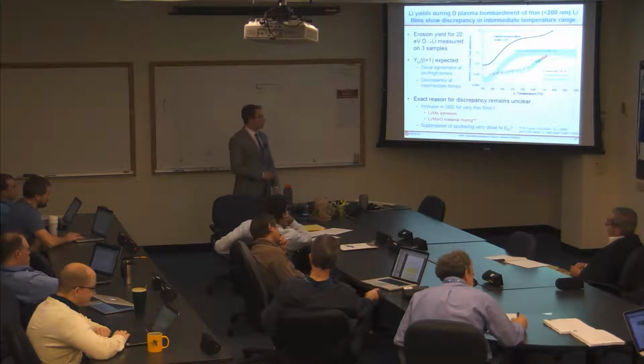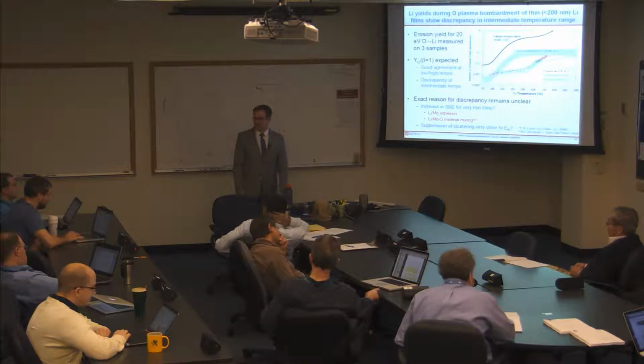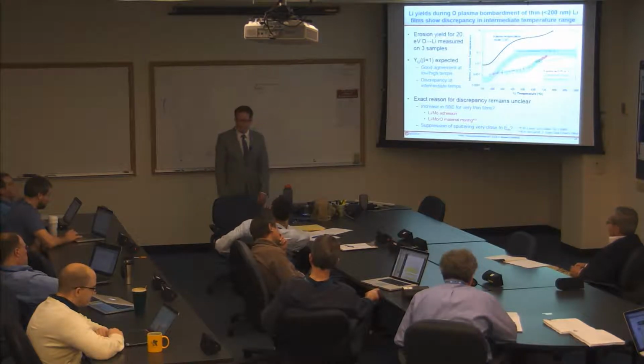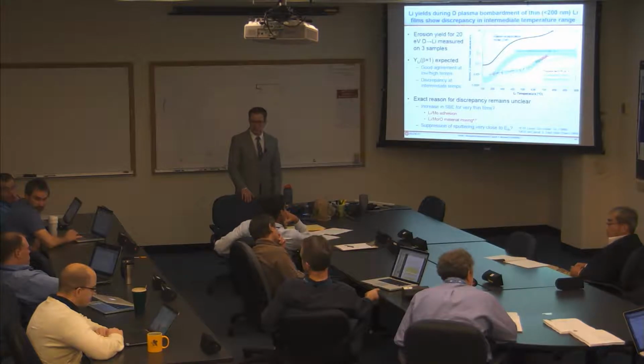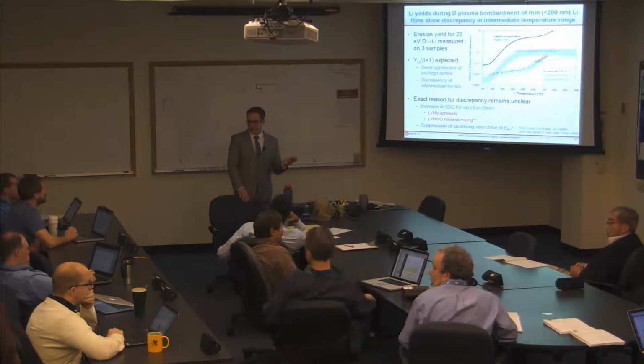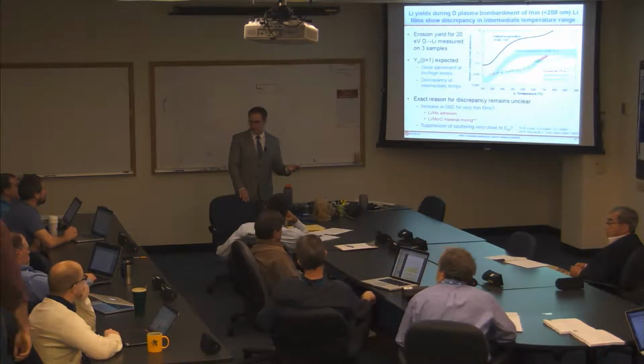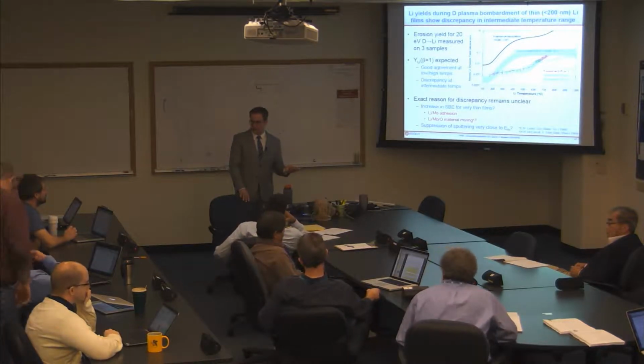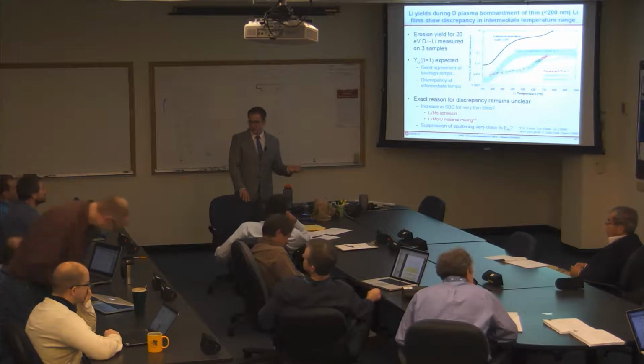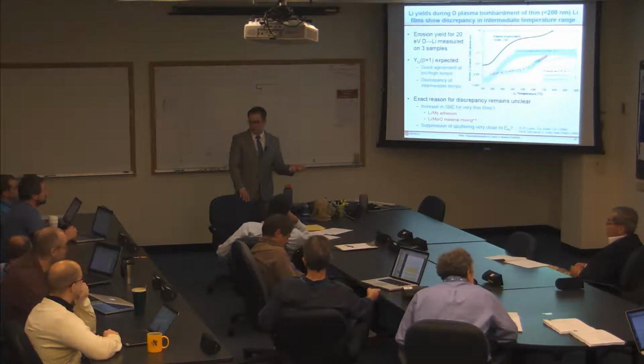We don't really see any oxygen emission in these discharges if you look at the spectroscopy. Really? Yeah. Any carbon? And those were evaporated in vacuum. Yeah, these are evaporated in vacuum. Remember, these are the in vacuo evaporation, not the preloaded. Okay, sorry. So we didn't do argon discharge cleaning on these, but they were not exposed to atmosphere before.